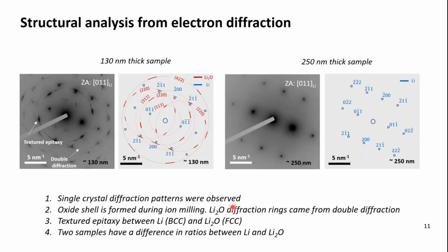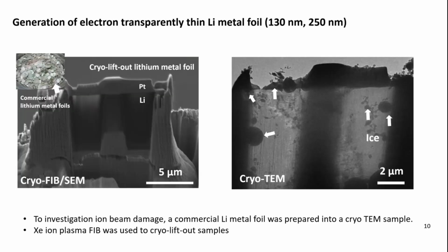Okay. Sorry, one last question as you're on this slide. It reminded me of a question from earlier. In this slide, you indicate that ice is condensed on this lift-out sample. Where did the ice crystals come from? Ice crystals tend to form when you transfer your sample from the cryo-FIB to the liquid nitrogen bath. Once you perform cryo lift-out and you have electron transparency, it's time to transfer your sample to the liquid nitrogen before you finally do cryo-TEM analysis.